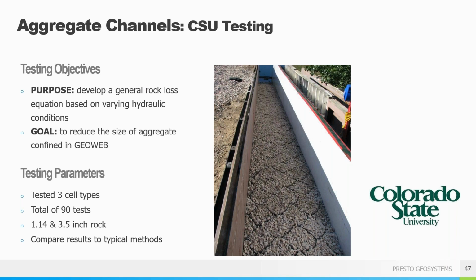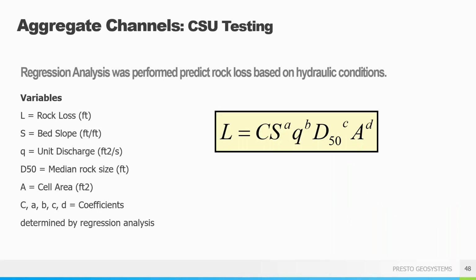So with the aggregate test, we ran a total of 90 different tests using 3 different cell sizes and 2 different rock sizes, with the goal being to develop a general rock loss equation based on varying hydraulic conditions. And with all of these data points, that allowed for the creation of a regression equation. So now, given the bed slope and unit discharge of a particular channel, we can manipulate the rock size and the cell size until we get to a point where your rock loss L is 0.